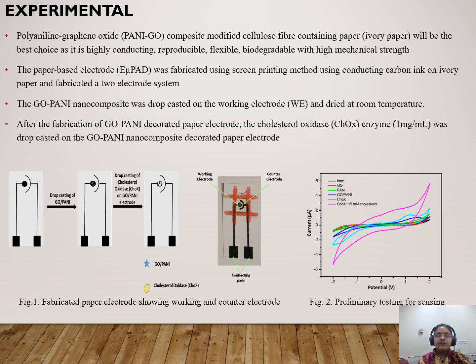Therefore this is the electrode which we have used, and we have carried out the first step of testing, in which we have taken the cyclic voltammetry measurements at each step. First one is the bare electrode, that is just a carbon electrode, this one, and then we have put GO on that, and we have taken the cyclic voltammetry measurements, in which there are no good peaks, it did not show very good electrochemical property.